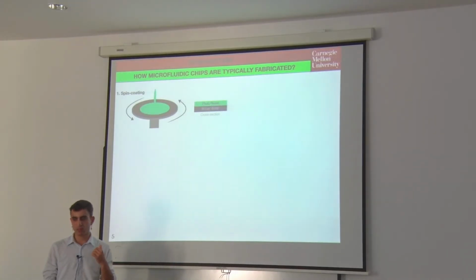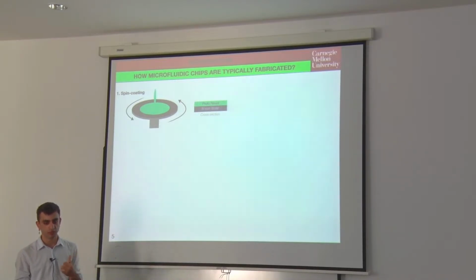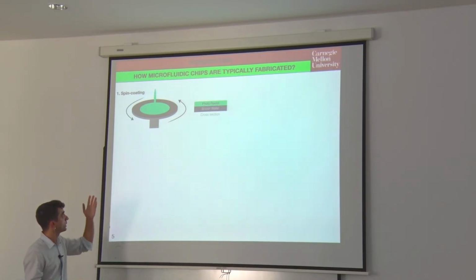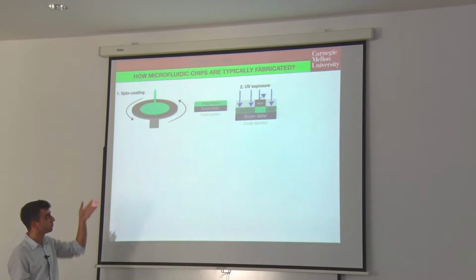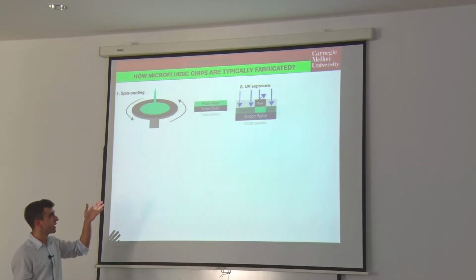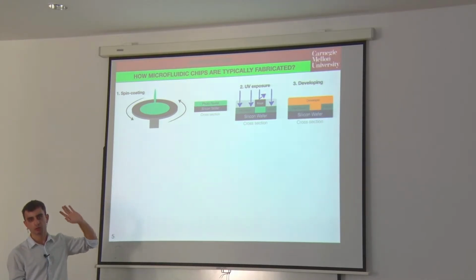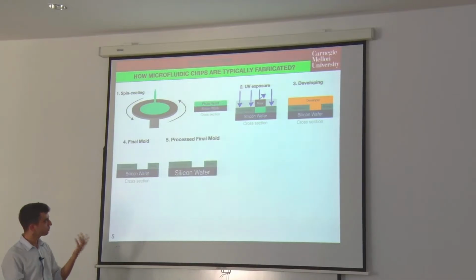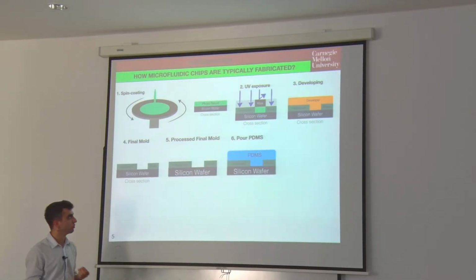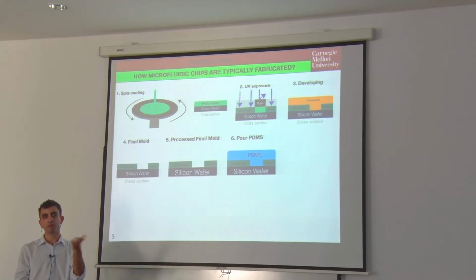And if we look at how we, in a nutshell, fabricate these microstructures, as I said, we borrowed them from the semiconductor industry. We get a silicon wafer, a semiconductor substrate, and we coat that with photoresist by spin coating. Then we expose this photoresist selectively to UV light using a mask, which hardens the photoresist, and we remove the non-hardened part of the photoresist, and we obtain a mold. We process that mold, and then we use a polymer called PDMS, polydimethylsiloxane, which is in liquid form, and if you mix it with a curing agent, over time, with the help of heat, you can cross-link it and make it solidify.